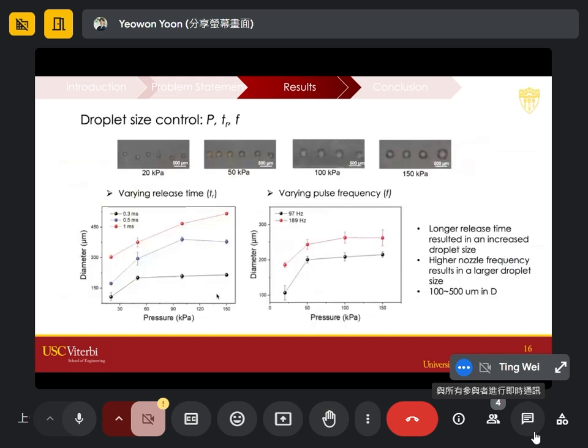Okay. The first thing we did is to control the droplet size. We learned that droplet size is dominantly controlled by 3 different factors, including pressure, nozzle release time, and the frequency of the solenoid valve. On the top figure, you see 4 different images printed with 4 different pressures. If you have a higher pressure, it pushes out more water, ending up creating big pores inside of the resin. The bottom 2 figures show varying release time.